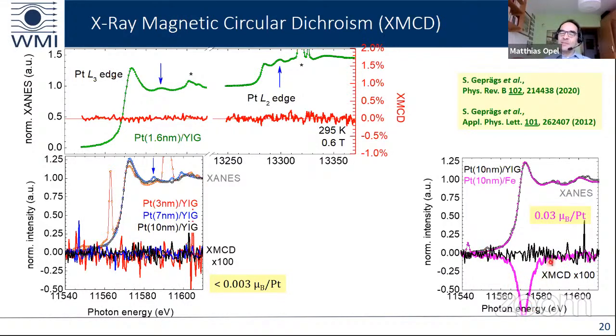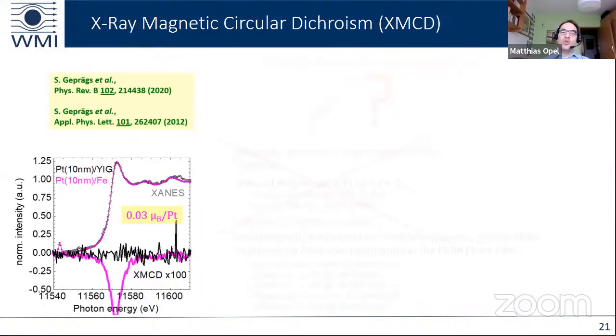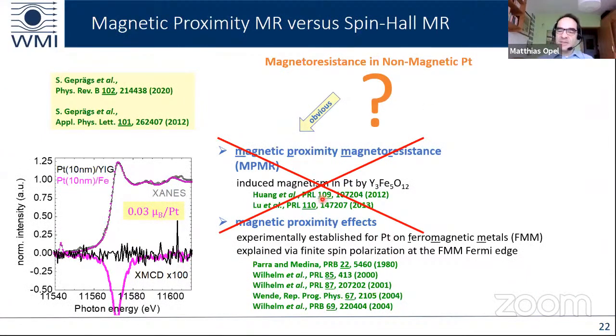So this XMCD signal tells us that platinum is really magnetic on iron, with a magnetic moment of 0.03 Bohr magnetons per platinum, but the platinum does not become magnetic on YIG. We were able to estimate an upper limit for the maximum magnetization of platinum which would be compatible with our spectra. And this is below 0.003 Bohr magnetons per platinum. So the platinum on YIG is not magnetic. The platinum on iron becomes magnetic. But then the magnetic proximity magnetoresistance could not be the right explanation for the magnetoresistance that we observed. So we had to look for an alternative explanation.